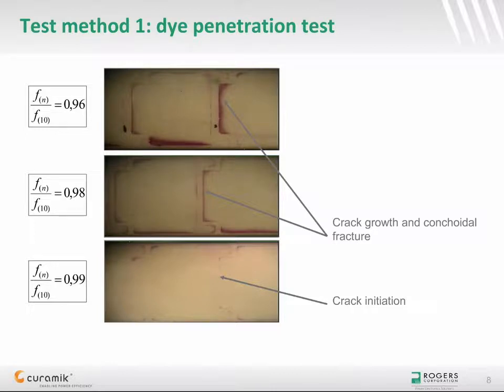Dye penetrant inspection is based upon capillary action, where low surface tension fluid penetrates into clean and dry surface breaking discontinuities. After adequate penetration time has been allowed, the excess penetrant is removed and a developer is applied to reveal the number and length of cracks. Of course, this is a destructive method, and the propagation of a crack for one and the same substrate cannot be observed as a function of the number of temperature cycles.